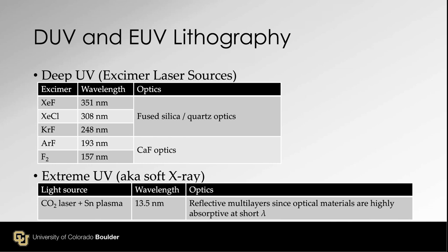In the deep UV time, we couldn't use any soda lime glass anymore, so you have to switch to fused silica optics. And for shorter wavelengths in the deep UV region, you have to switch to calcium fluoride optics. In the X-ray region, absorption is too much, so you cannot use the conventional transmission mode of pattern transfer anymore. So you have to use reflective multi-layers for the extreme UV optical lithography or photon-based lithography.